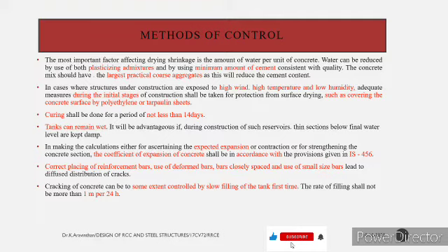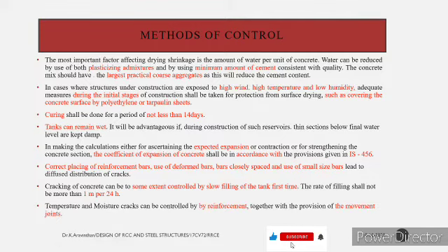If you are filling the water tank for the first time after construction, the rate of filling shall not be more than 1 meter per 24 hours. Temperature and moisture cracks can be controlled by reinforcement together with the provision of movement joints. Okay, right now we have discussed the major considerations while designing.